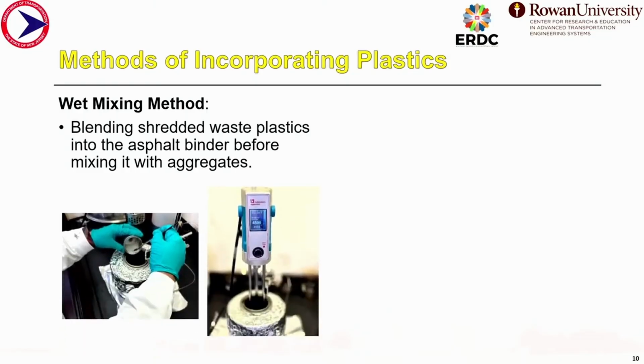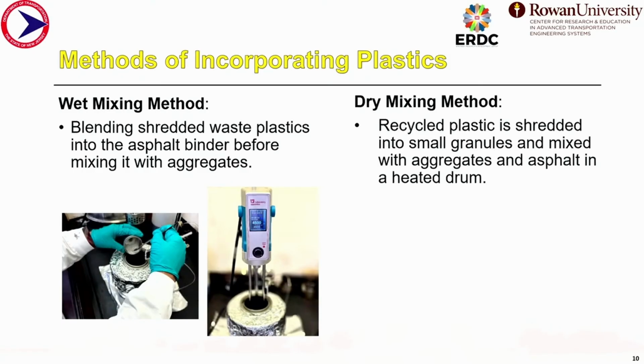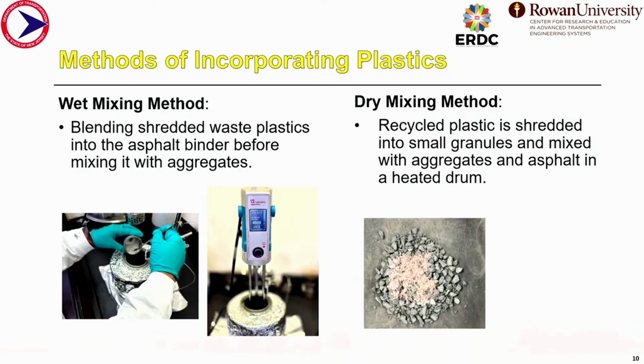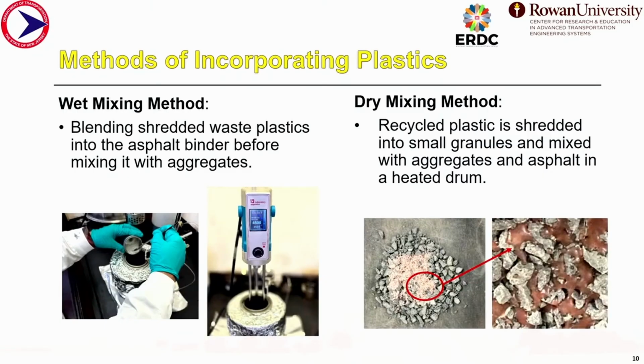In the wet mixing method, we have to mix these shredded plastics into the hot asphalt binder using a high or low shear mixer, and then we have to put it into the hot aggregates to prepare the HMA mixture. On the other hand, in the dry mixing method, we put the plastics directly into the hot aggregates, and then we add the hot asphalt binder, and then we prepare the asphalt mixture. And here we can see, in the dry mixing method, how these plastics are coating the aggregates.